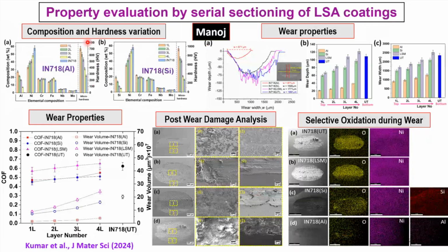So he did a very careful analysis going layer by layer, taking serial sections parallel to the surface at certain micrometer depths - first layer, second layer, third layer, and so on. In all these bar diagrams you'll see the composition for various elements, whether it's silicon alloyed or aluminum alloyed.